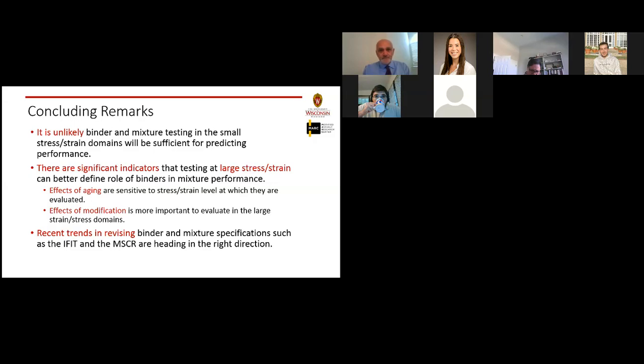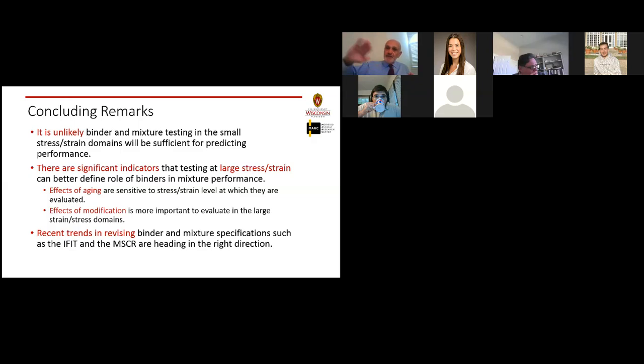Thank you. Okay, so this is a very interesting question, Mahdi. I'm sure you're familiar with the MEPDG and the rutting model in the MEPDG, which gives you the plastic strain as a function of the initial elastic strain in a power law. In fact, if you do the right testing in the DSR, you can capture the exact same behavior. Now, binders don't go into tertiary flow, but binders do go into an initial creep, and then they go into a secondary creep. And that secondary creep actually continues for a long period of time. And we can actually capture the steady state creep behavior of the binder.